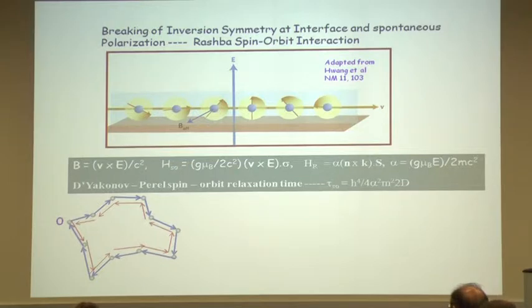consequence of this spin orbit interaction is in the diffusive motion of electrons. For example, if you have a two-dimensional electron gas, and you consider an electron at point O, and you consider two partial waves, one is going in the clockwise direction, and as it goes, it scatters from these impurities. These are purely elastic scattering. So during the scattering process, there is no change of phase. And you consider another partial wave which is going in the counterclockwise direction, and when these two partial waves meet at point O, you have constructive interference. And because of that constructive interference, the backscattering probability of electron goes up.